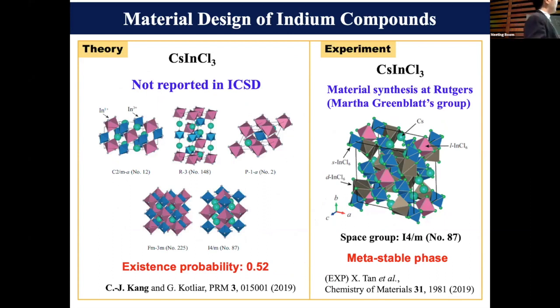The computation also predicts that I4/m is a possible candidate structure. However, both of them are not the same. We computed their total energy and found that the theoretically proposed structure has lower energy than the experimental one. So we found that the experimental crystal is a metastable phase.